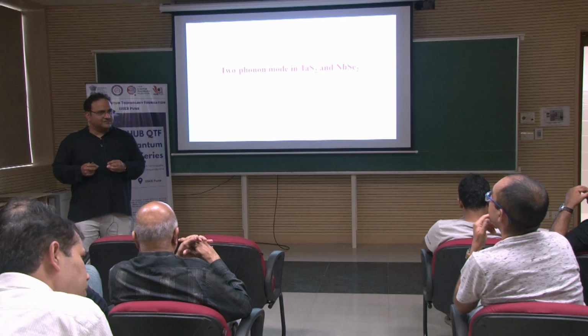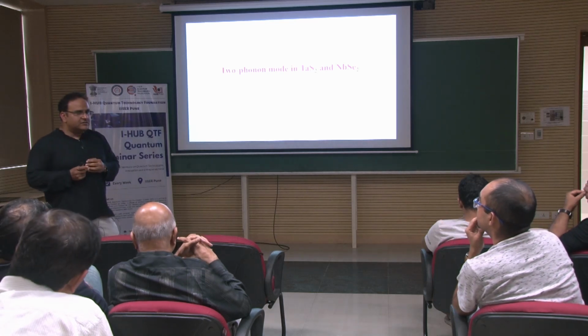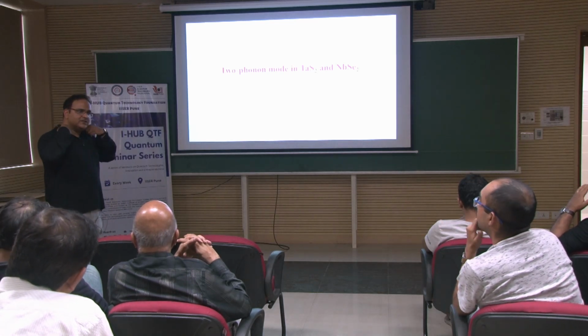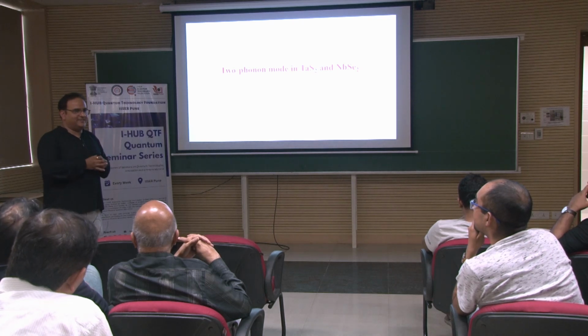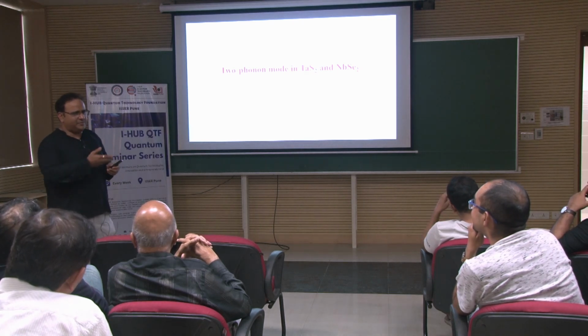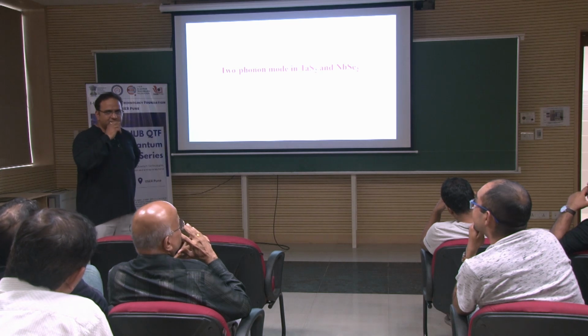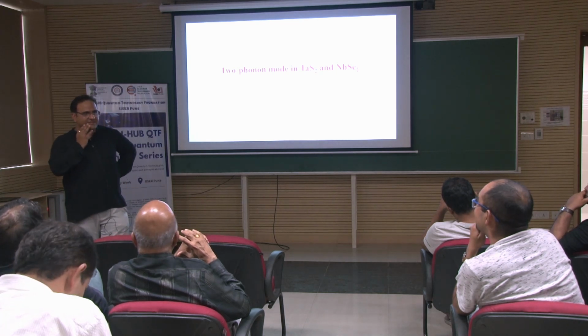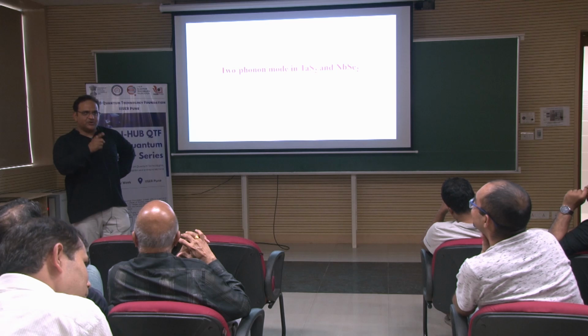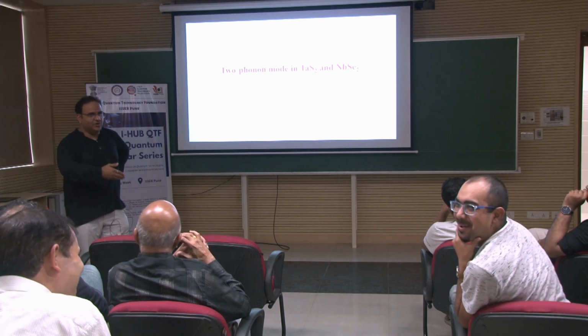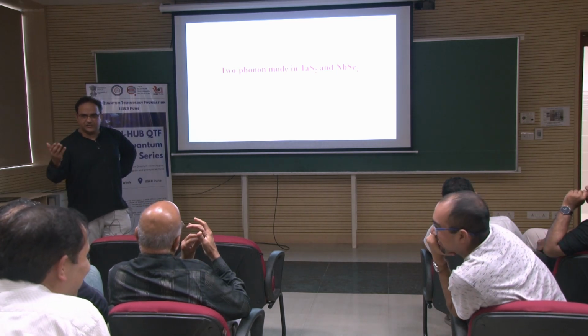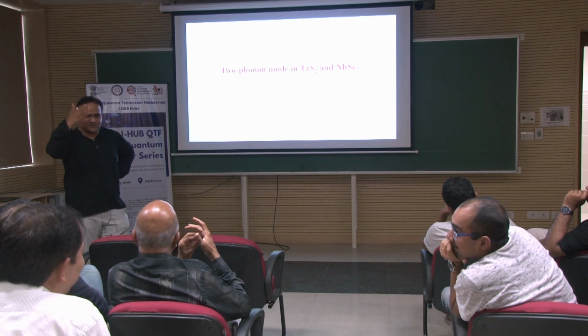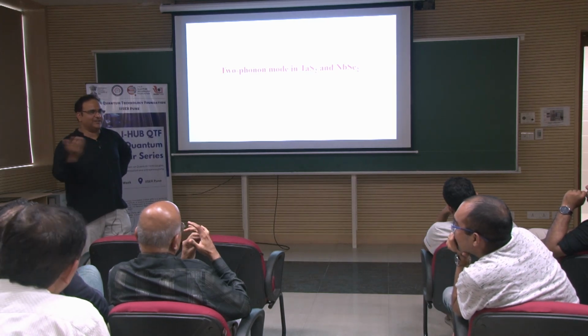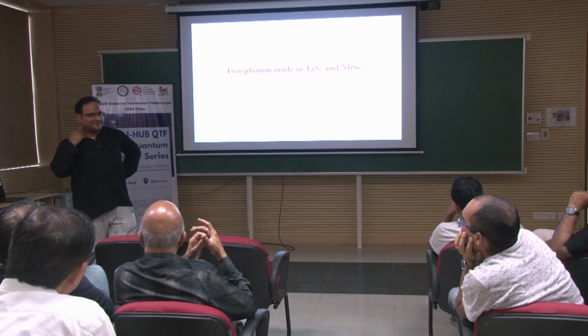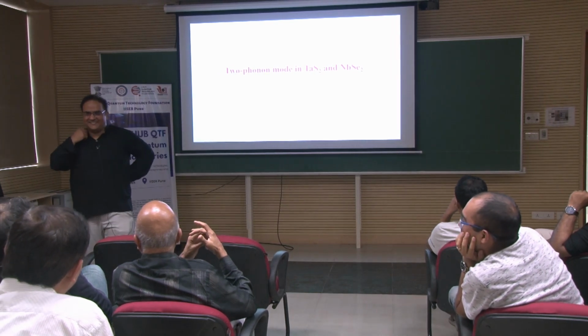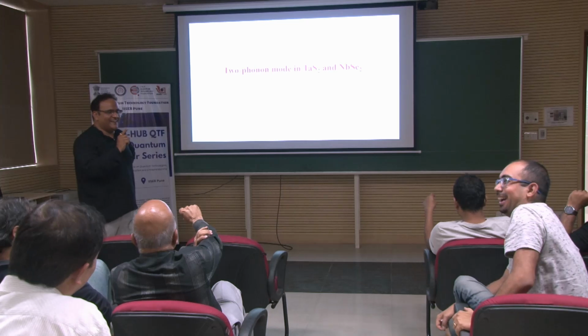So do we know in these materials the energy of the acoustic phonon? You do the calculation; experimentally people have done it with neutron scattering. See, neutron scattering or Brillouin scattering, you go beyond Q equals 0. Our struggle is Q equals 0; we can't go beyond that. So do we find something around 80? Sorry for pushing you. No.